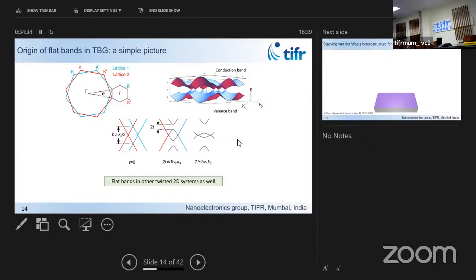Is this under the limit that the free electrons on both the lattices are not strongly interacting? No, they are interacting. If they don't interact with each other, then you won't get this physics. The exciting physics happens only because the electrons are hopping between the two layers. If they are electronically decoupled, you basically get two copies of this and none of the exciting physics. The fact that the electron has to hop from one layer to another at different sites causes this hybridization. So in the language of chemistry, you have electronic states here that cross, but the interaction hybridizes these bands. Those gaps are some sort of coupling between them. Yeah, it's because of the coupling.